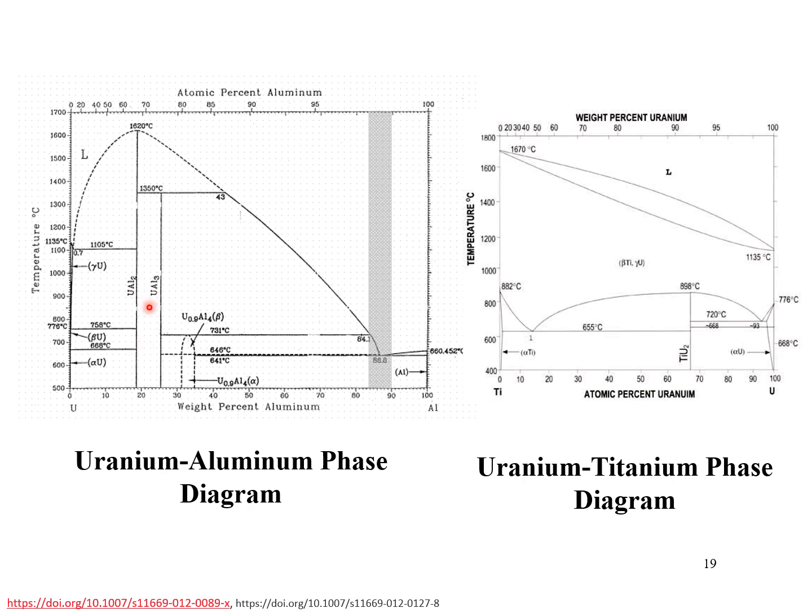If we mixed uranium by weight with 25% aluminum, it would fall right about here, and we would have a mixture of compounds based upon where it falls on this phase diagram. Over here, the 25 would be primarily UAl3 with a little bit of UAl2.